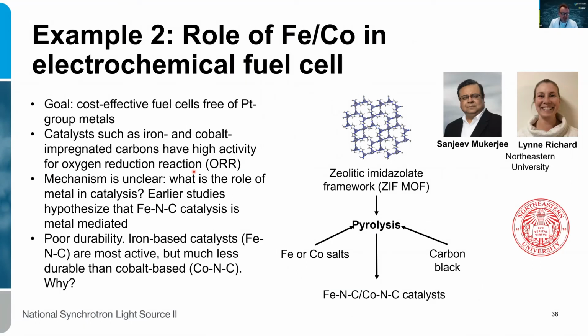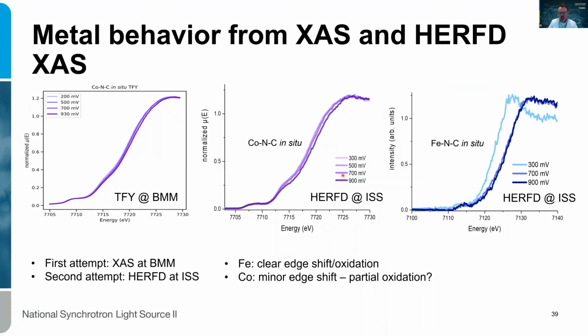The other example is electrocatalysis, where our users, like many others, are trying to invent a replacement for noble metal electrodes, for oxygen reduction, for hydrogen evolution, all those things that are relevant for water splitting and artificial photosynthesis. These iron and cobalt catalysts are pretty popular for this matter. They're usually prepared by pyrolysis of metal organic frameworks, in addition with the salts of the materials, and you get sheet-like materials where the iron and cobalt is incorporated in those sheets of carbon and nitrogen.